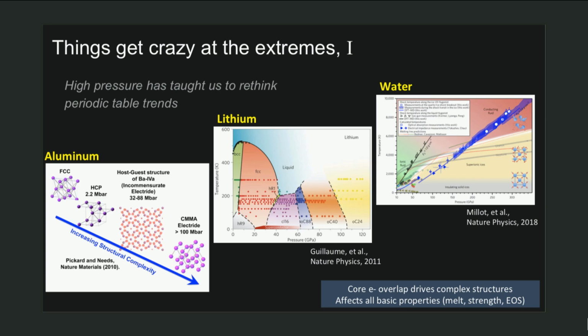And so we find things like host-guest structures where there are two interpenetrating lattices. We find electrides, which is when you have a valence pair come together and then pop into an interstitial site, and it causes, for example, sodium to become transparent because you have an electron pair acting as what an atom would otherwise. And you have superionic ice, where you have a lattice of oxygen atoms with delocalized hydrogens bouncing around, and that's a different charge carrier completely.